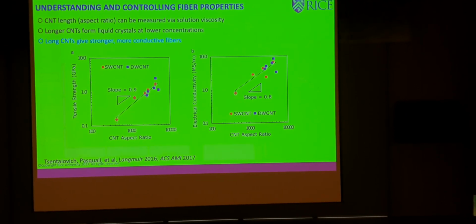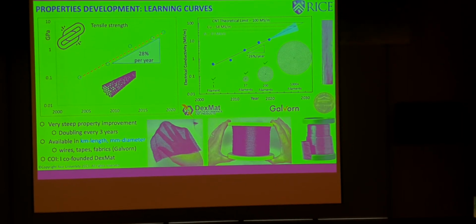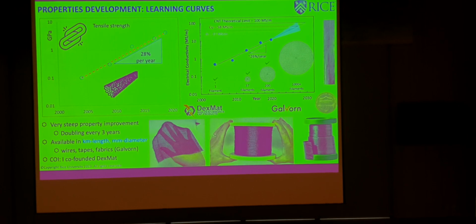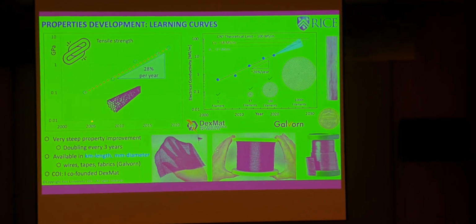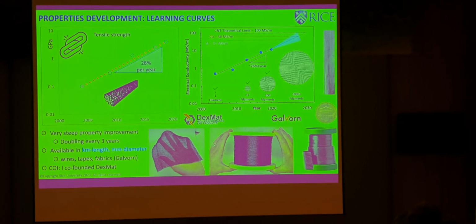Now, you can look at this a little bit differently. You can look at this, how did we do versus time? And I started putting this together only recently. And the reason I put only stuff from our lab is because this one I can swear by. Every one of these points was measured in at least two labs. Even at the beginning, everything was measured both by Jack Fisher at Penn and by us at Rice. And so we see that both the strength and the electrical conductivity essentially doubled every 3 years. Partly because of better processing, partly because of longer nanotubes becoming available via collaborations.